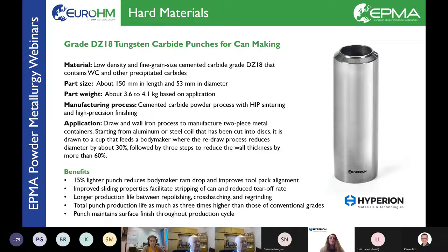The use of a lighter cemented carbide punch leads to a reduced body maker ram drop and to an improved tool pack alignment. As a consequence, the tear off rate, or can breakage rate, is reduced and the punch maintains its integrity for longer, exhibiting a production life 3 times higher than those of conventional carbide grades. Kenan, next slide, please.